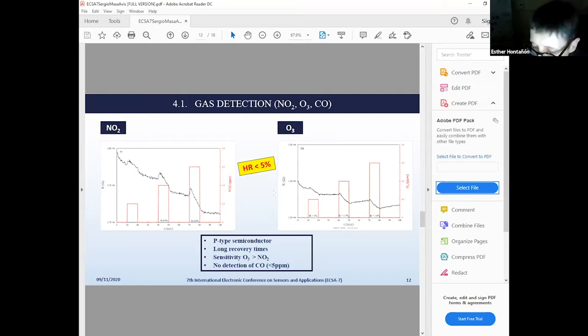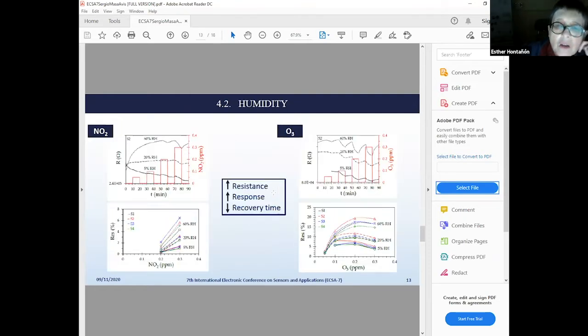So now we studied the effect of the air humidity on the sensing performance of this sensor, based on these electrospray reduced graphene layers, and we observed that the humidity has 3 major effects. First, the resistance increases. In the top figures, you can see the evolution of the dynamic resistance of one of the sensors for different concentrations of the gas in the mixture, and also different levels of air humidity. You can see that by increasing the humidity, the resistance of the sensor increases too, but also the sensor response. Here you can see the sensor response to different levels of nitrogen dioxide and different levels of air humidity.